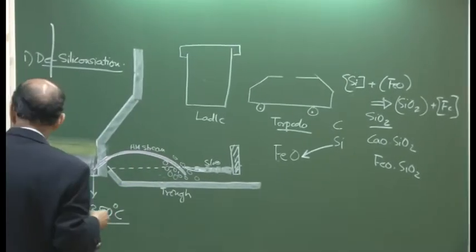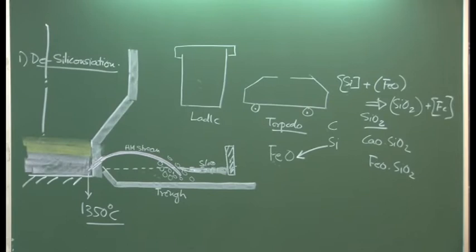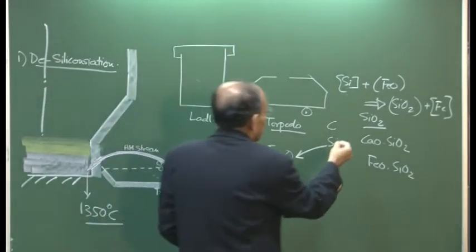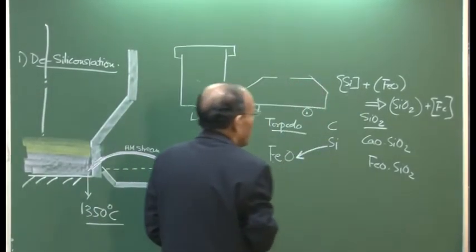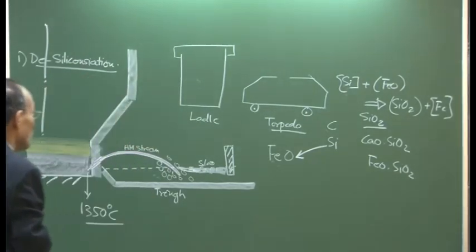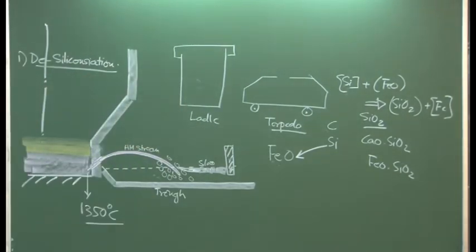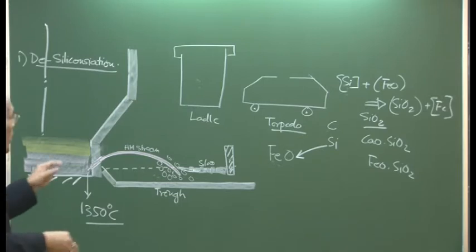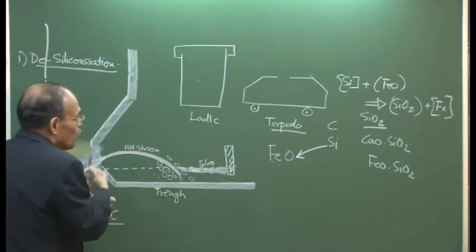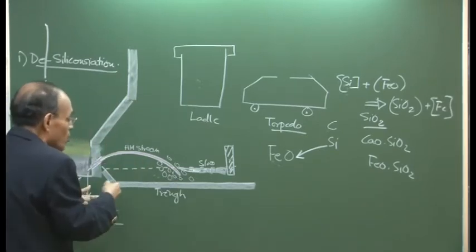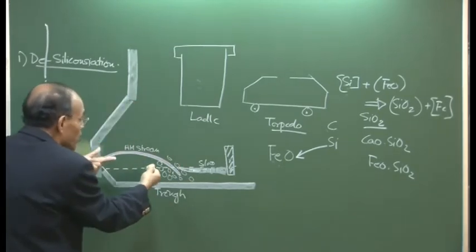And then, through stoichiometry, we should be able to also see how much FeO is to be added to reduce, eliminate silicon, and all these calculations will tell us that we are taking advantage of the existing scenario. We do not have to do anything to introduce stirring. High temperature is already there, these are the prevalent scenario.